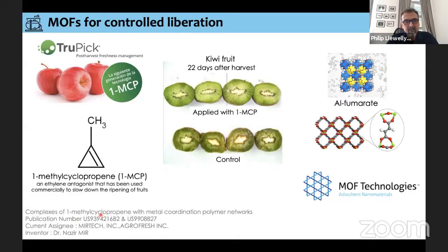So there's a patent from Dr. Nazir Mir using this molecule in a metal organic framework. If you go to this patent and try and work out what is the actual MOF used, it's not easy to see, but I'm guessing that it's this material, an aluminium fumarate type MOF. It's one which has quite small pores. Aluminium is quite a cheap metal, and the fumarate linker is also quite cheap.